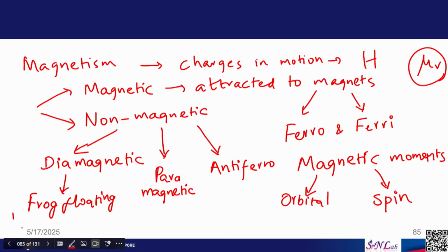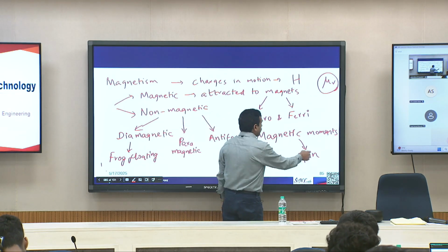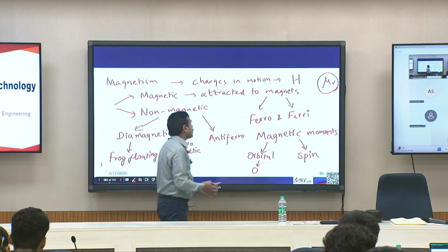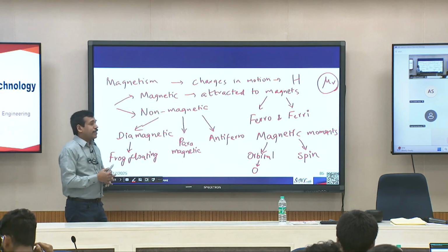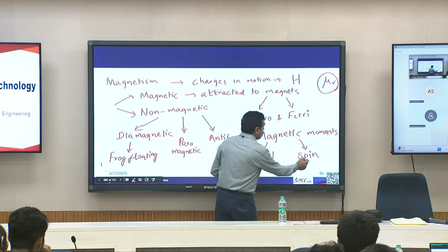Okay. So we have these two properties, and I told you that in materials like iron, cobalt, nickel, when you place them in a solid state, the orbital moment is quenched, basically it is 0. No contribution. So it is the spin that will finally give rise to the atomic magnetic moments. It is not just spin, it is the uncompensated spin.